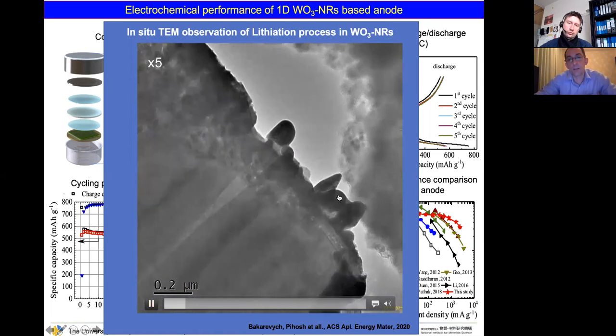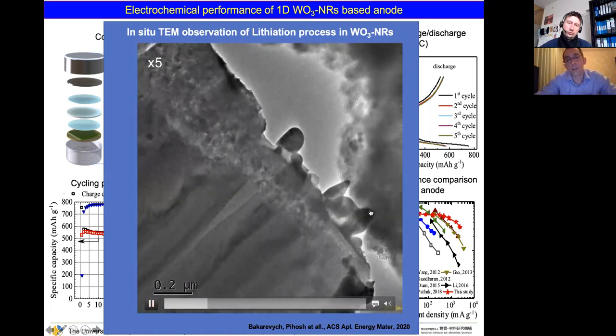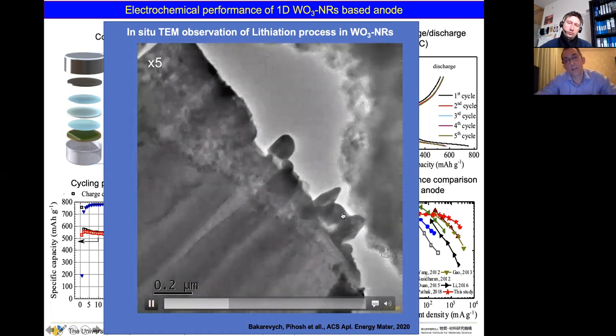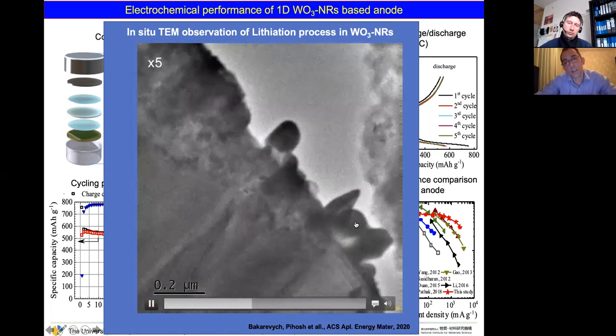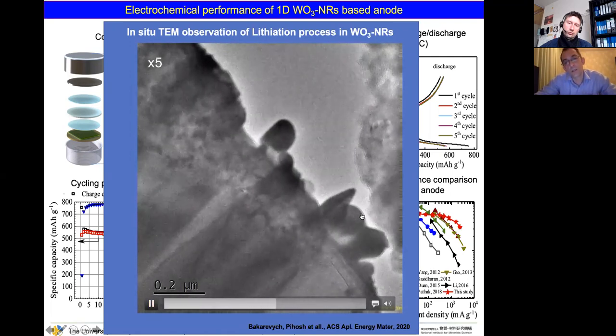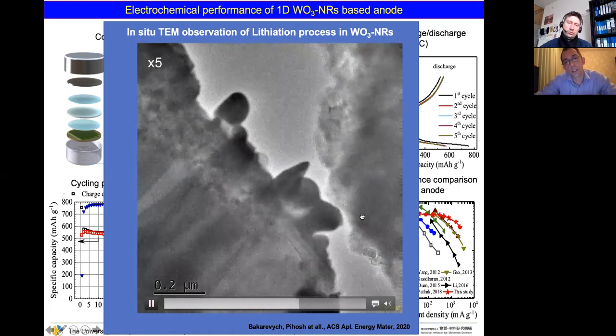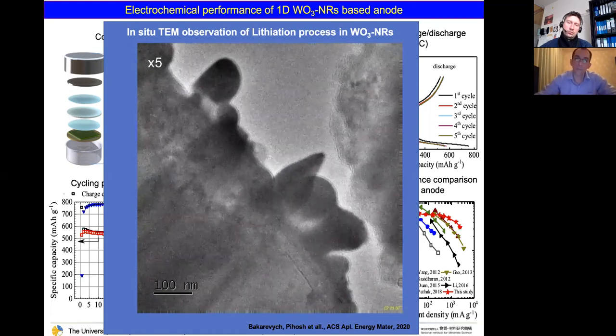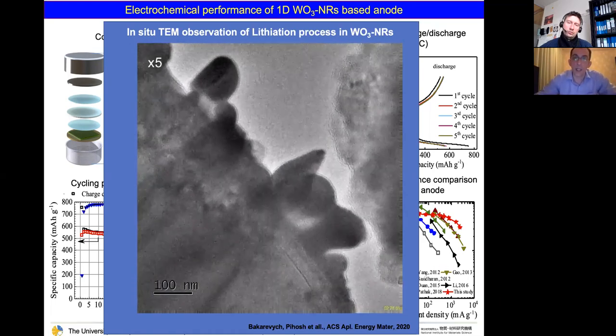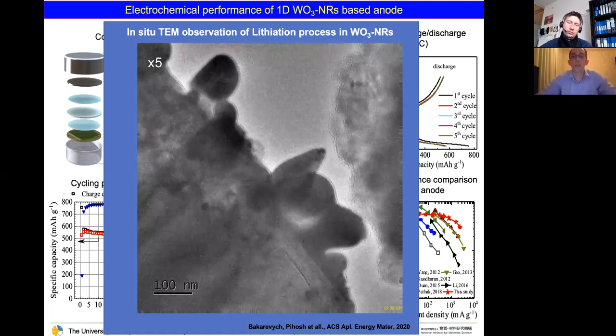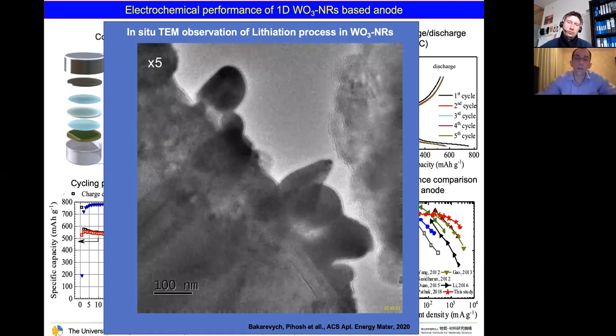So this is nanorod and this is lithium material. So when it's in contact, applied some voltage. What we can see here, this is expansion of the nanorod. Okay, it's very nice to see. And in the case when the lithium is released from the tungsten oxide, this nanorod returns to the previous stage. So actually, this is some kind of nano breathing anode.